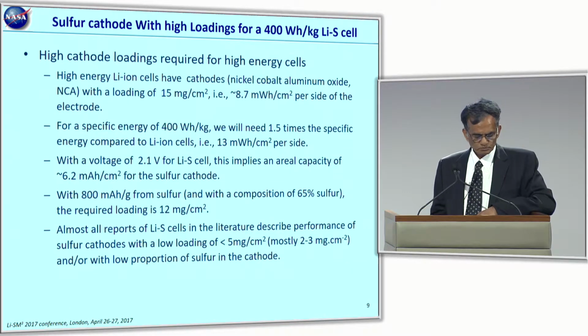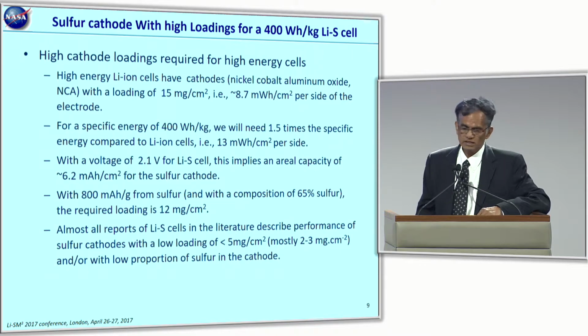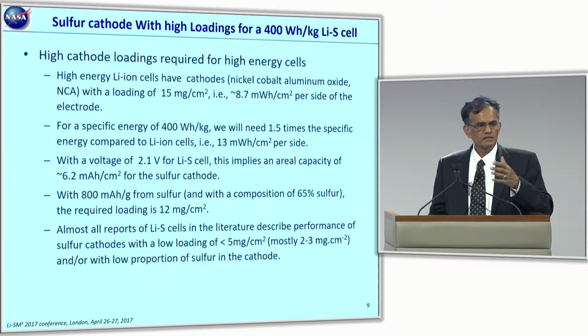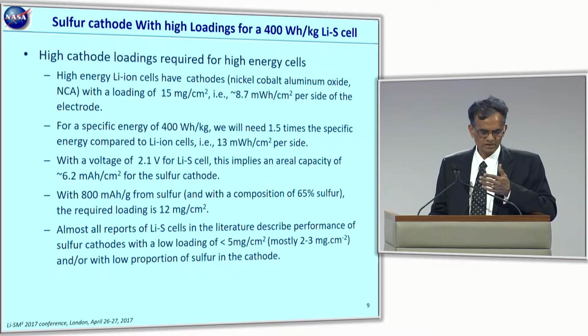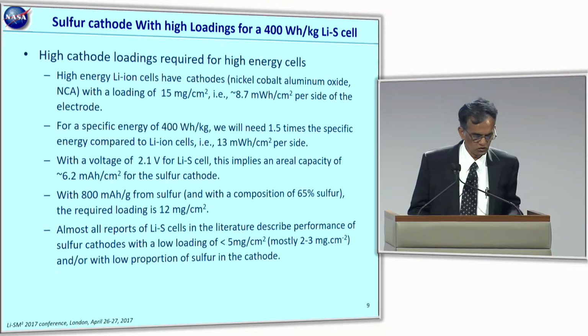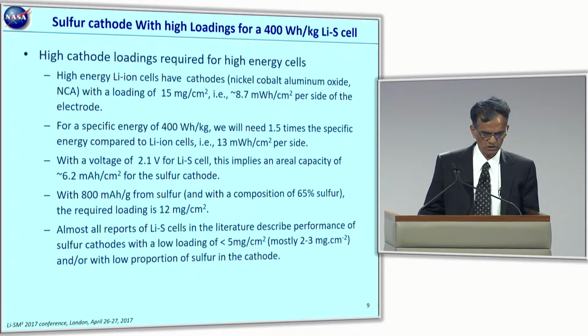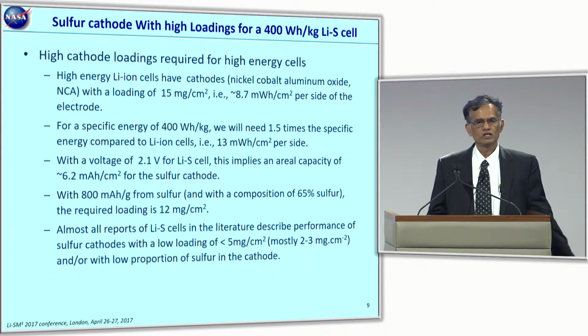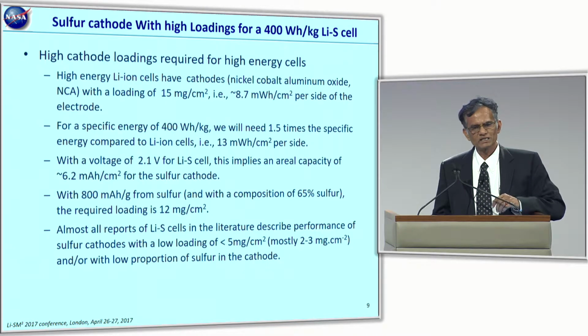The logic being, if we take the numbers from the lithium-ion chemistry, today's high-energy lithium-ion cell has a loading of 30 milligrams per square centimeter. That is, per side, about 15 milligrams per square centimeter, combined with its 4-volt system. So we're talking about 8.7 milliwatt-hours per square centimeter. And we know that today's lithium-ion chemistry can provide 250 watt-hours per kilogram. So we are talking about at least 1.5 times improvement in the specific energy. To achieve that, we need to have 13 milliwatt-hours per square centimeter from the sulfur cathode.